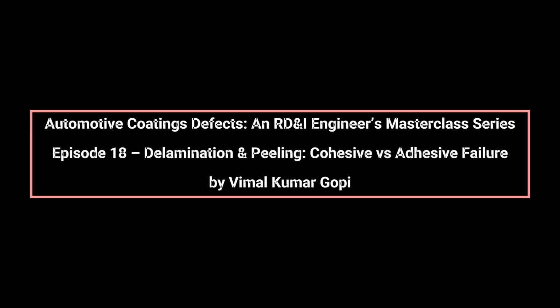Troubleshooting delamination requires forensic discipline. Tape tests alone are insufficient. They indicate only gross adhesion. Cross-section microscopy, fracture surface analysis, solvent rub tests, and environmental aging data must be correlated with process records. Identifying whether failure is adhesive or cohesive guides corrective action: surface preparation, flash-off, and contamination control for adhesive failures, formulation balance, bake tuning, and film build control for cohesive failures.